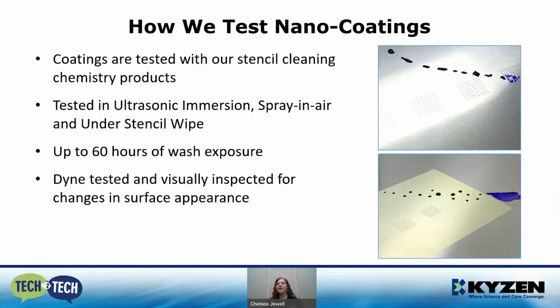And what you'll start to see is on our nanocoatings, that solution beads up and you have a lot more surface tension to raise that fluid off. Whereas once you go into the non-nanocoated areas, that solution wets out and it's flat in appearance. This is how we check to make sure that the coating is holding up. Also, with our cured coatings, we check for visual differences.